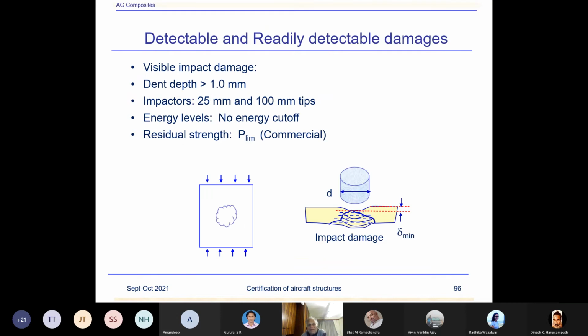Okay, readily detectable. So I did talk about detectable damages and RDDs, readily detectable damages. So visible impact damage, which normally has dent depth greater than 1 millimeter. Impactors could be larger here, 100 millimeter tip and 25 millimeter tips. Energy levels: we've said for BVID or undetectable damage, the energy limit was 140 joules, whereas for this one, there is no energy cutoff.